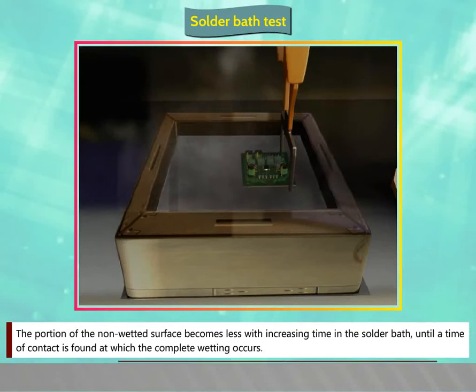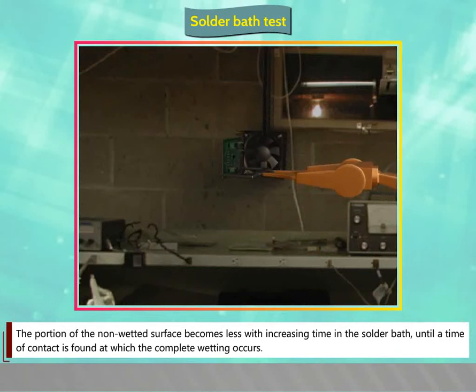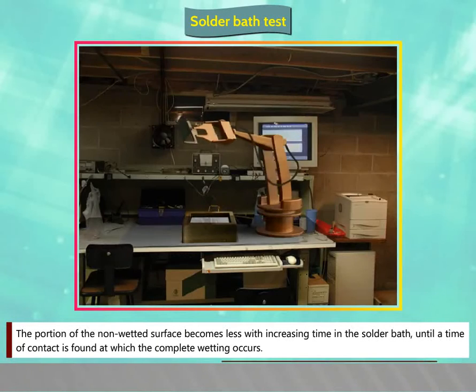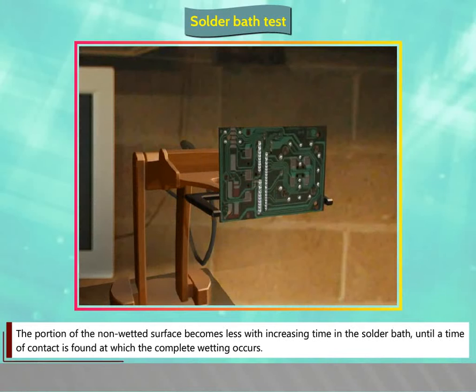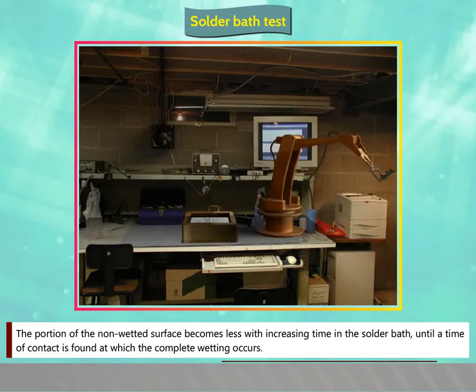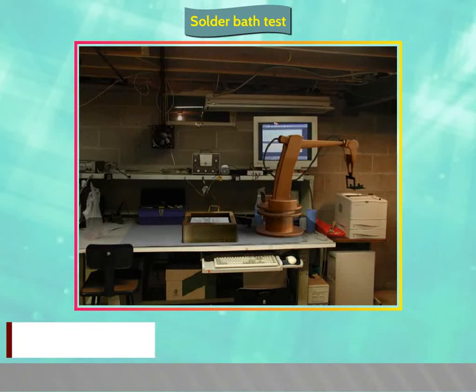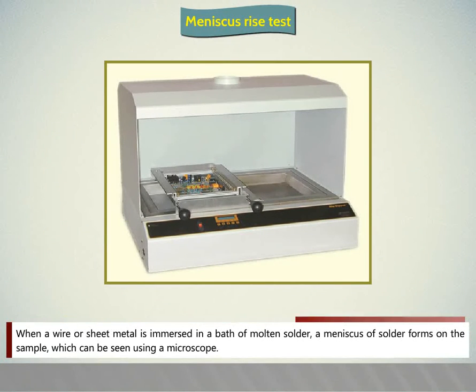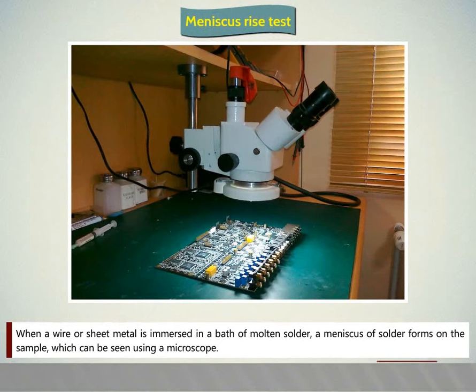The testing apparatus has a horizontally rotating spindle and a radial arm to carry the test pieces horizontally and face down across the surface of the solder bath. The portion of the non-wetted surface becomes less with increasing time in the solder bath until a time of contact is found at which complete wetting occurs.